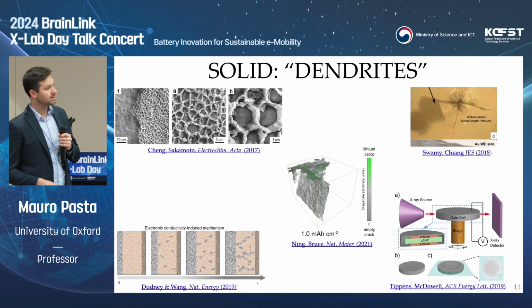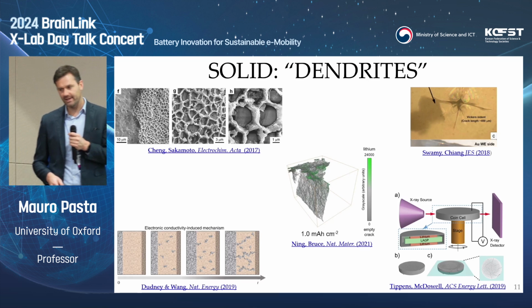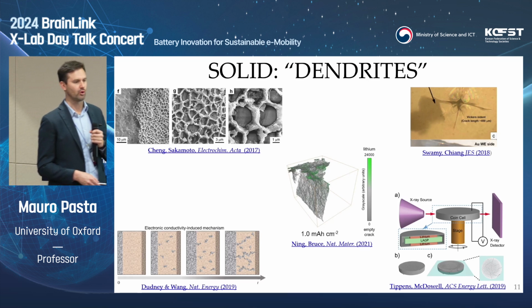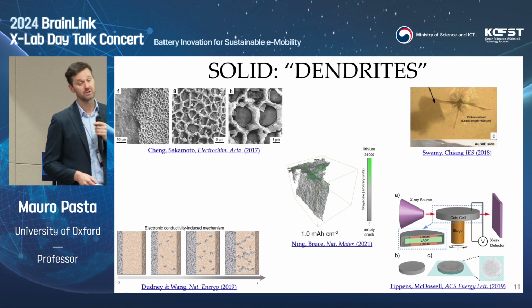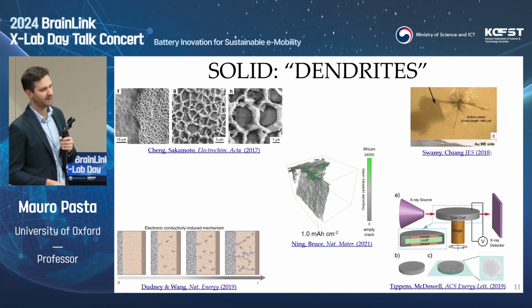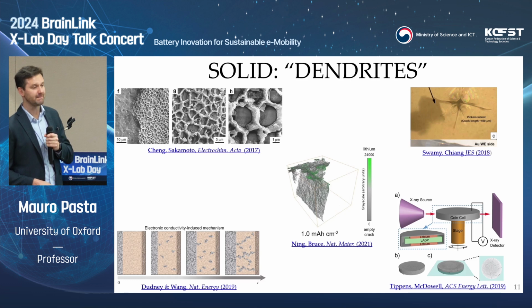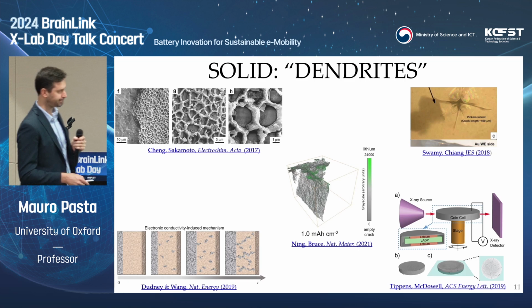Now, it turns out that even in the case of a solid electrolyte, you do form something that looks like a dendrite, even if it's not a dendrite. So you do have catastrophic failure even in a solid. This is due to the formation of filaments of lithium that still propagate through your solid electrolyte and short circuit. They are often still referred to as dendrites, but are not necessarily dendrites. Their outcome is quite similar, so they lead to short circuiting.